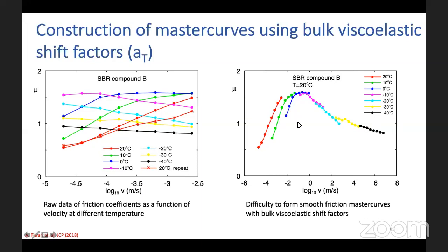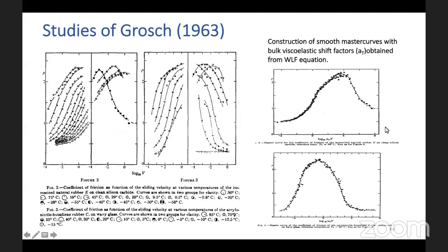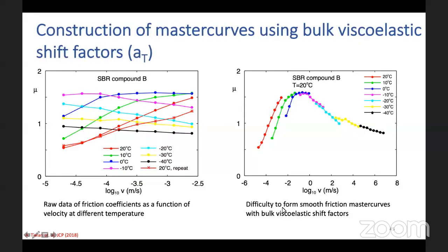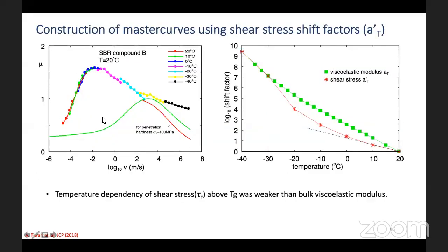So when we use the bulk shift factors obtained from the viscoelastic data of this material, we are not able to form a smooth master curve as formed by Grosch. Here, Grosch is able to form smooth master curves, but we were not able to form smooth master curves. So what we did was we shifted the curves anyhow and we formed a smooth master curve.